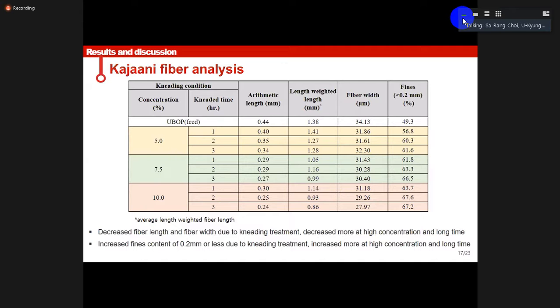The results of the Kajaani fiber analysis showed the same tendency as the result from the optical image. Fiber size under 0.2 mm was defined as fine content, and the average of the fiber length and fiber width over 0.2 mm was shown in the table. The fiber length and fiber width decreased due to the kneading process, and the higher the concentration and the longer the time, the more the fiber size decreased. Also, when the pulp concentration and kneading time increased, the fines content was higher and the fibrillation effect was improved.